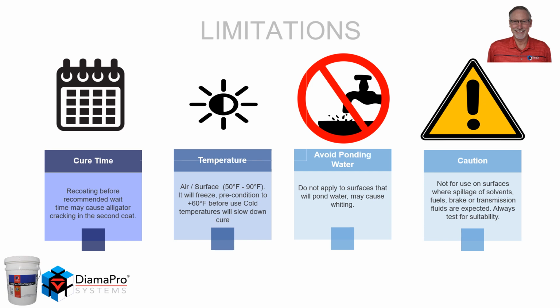Once it's applied, you want to stay away from ponding water. The material is breathable, so it allows moisture from the concrete to come up, but also it allows moisture from above to go in. So if ponding water is there for a long extended time, it could be absorbed into the film and cause a white hazing. And when it comes to protection from solvents such as brake fluid, gasoline, transmission fluids, this is not the system to utilize for that type of protection. But during your mock-up phase, you can always test different chemicals to see how they will react.